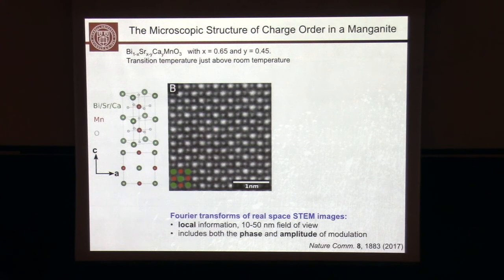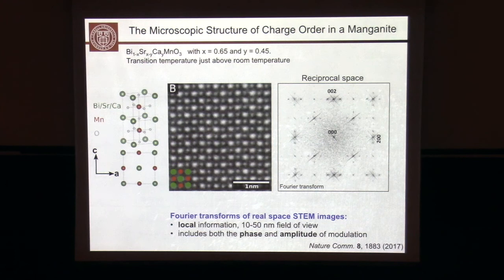OK, so here's now what we have done. This is a manganite that we've selected because the phase transition is right above room temperature. That is really good because we can first assess how order occurs near the transition temperature and then far away as we cool. So this is the atomic structure image in a scanning transmission electron microscope. It already includes local distortions. The way we know that is by taking a Fourier transform of a real space image, and you again see the superlattice modulation that decorates our Bragg spot. Now, the advantage of Fourier transforms compared to diffraction patterns is that a Fourier transform is typically over very small areas.